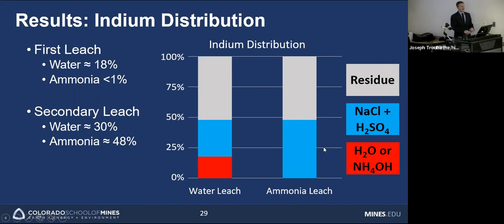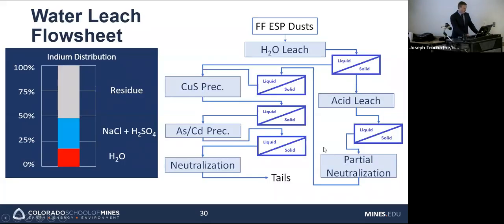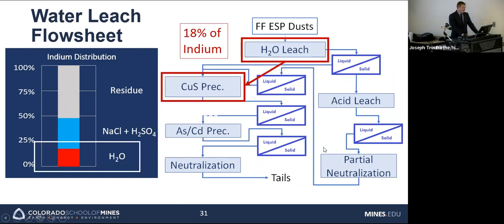But the question is, does it matter that the streams split? Obviously, we're trying to create a concentrated stream for recovery. So let's look at the flow sheets. Here's the water leach flow sheet. 18% of the indium was leached during water leaching. This is passed through a sulfide precipitation step, and then this sulfide is returned to the smelter.